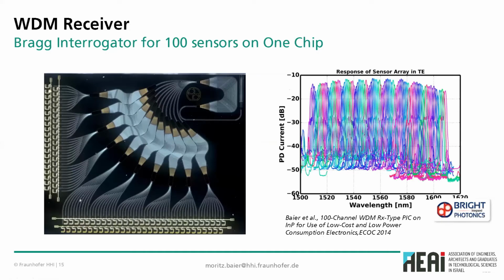Another example that I like to show to address questions about yield is this 100-channel fiber Bragg interrogator that is based on 11 AWGs and 100 photodetectors. So in total you have 100 channels, each spaced by 1 nanometer. So it's a 100 nanometer wide interrogator. And as you can see from this rather messy plot, if you count and look very closely, all the 100 photodetectors work. And if I were to make this plot even more messy, which I did not for clarity on the slide, and overlay the simulation of the designer, which in this case was Bright Photonics from the Netherlands, over the experimental results, they match exactly.